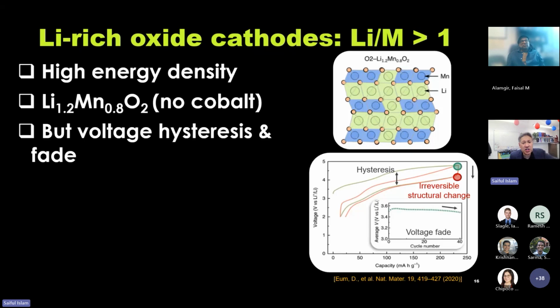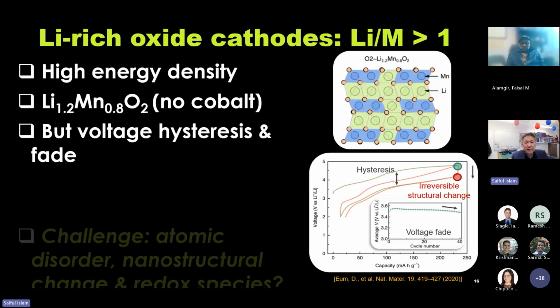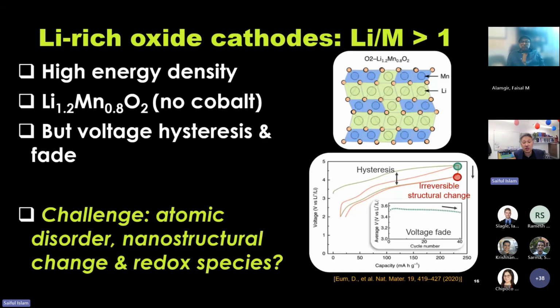So what's the advantage of these materials? Well, the advantage is the high energy density. There's no cobalt, there's no nickel, so we've got a much more sustainable material. But as I've said, there is voltage hysteresis and capacity fade. So the challenge is, can we understand what's going on at the atomic level? There are some atomic structural changes. Can we understand the nanostructural change? And what is the redox species in this material?